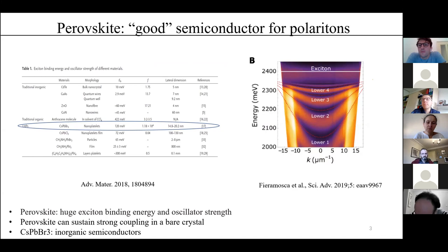Then as you see, there is a change of the dispersion relation in the subsequent resonances due to the presence of the exciton. But this change, in my opinion, is due to the fact that there is an abrupt change of refractive index close to the excitonic resonance. And since the refractive index increases, the effective mass of the mode also increases. So closer to the resonance, you have higher refractive index, so you observe this kind of behavior, and, for instance by the Berreman method, even without strong coupling, just by having this dispersion, you can observe such curves.